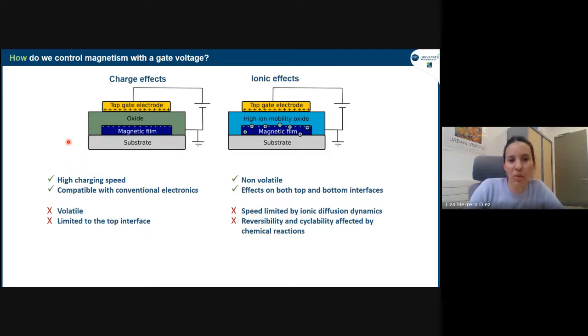And this is really what we do when we use charge effects. So the good thing about this is that it has high charging speeds because it's all electronics, and it is compatible with conventional electronics, and of course more compatible with any kind of application. However, on the downside, it is a volatile effect. So if you switch off your gate voltage, then the effect is gone. There's no more charge accumulation. And it is limited to the top interface.